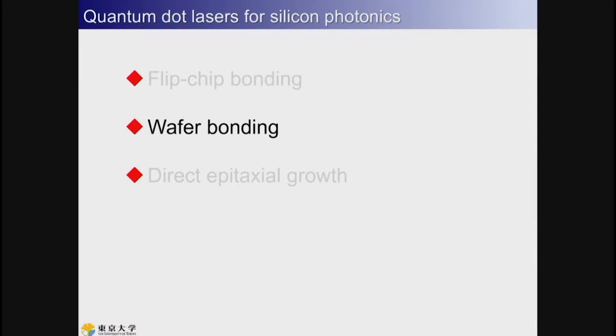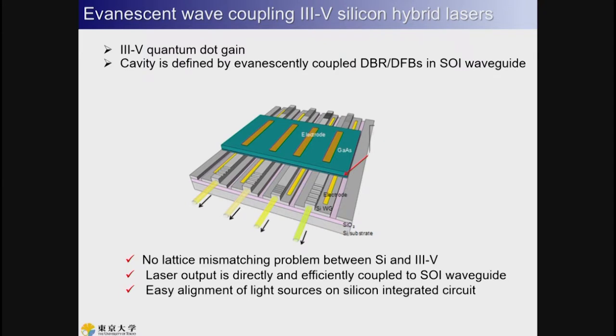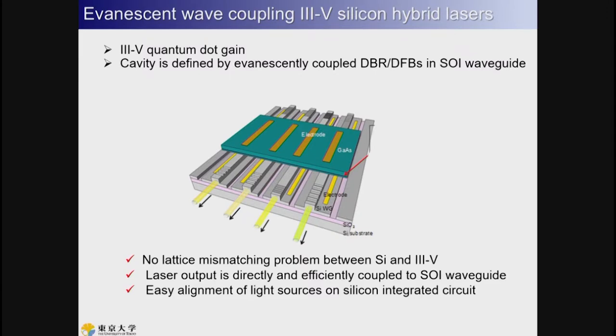But we are working at a university, so we are also investigating next generation methods, the wafer bonding and also direct epitaxial growth techniques. First, I will briefly describe the wafer bonding technique for realizing array lasers. We are utilizing evanescent wave coupling in III-V silicon hybrid laser structures. The gain III-V materials and the cavity defined by evanescently coupled DFB or DBR structures are in the SOI waveguide. Of course, in this case, there is no mismatch problem between silicon and III-V technologies. And the laser output is directly and efficiently coupled to the SOI waveguide if we realize this kind of structure. The alignment is very easy.